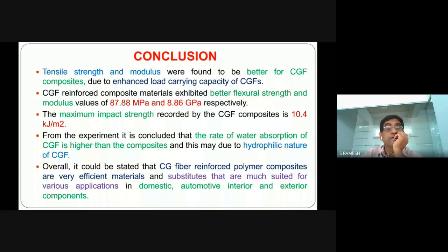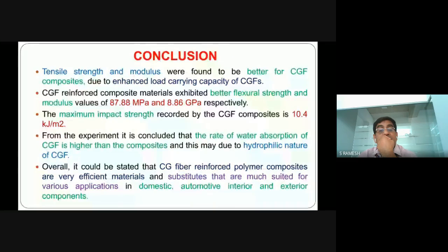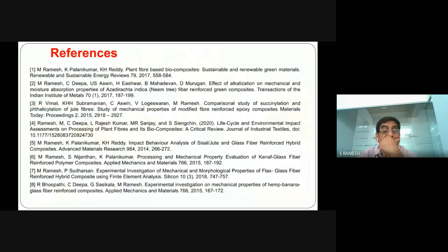From the experiment, it is concluded that the rate of water absorption of the Calotropis gigantea fiber is higher than the composite. It is mainly due to the hydrophilic nature of the fiber. Overall, it can be stated that Calotropis gigantea fiber reinforced polymer composites are very efficient materials and substitutes, well suited for various applications in domestic, automotive, and interior and exterior components. These are the references we used.